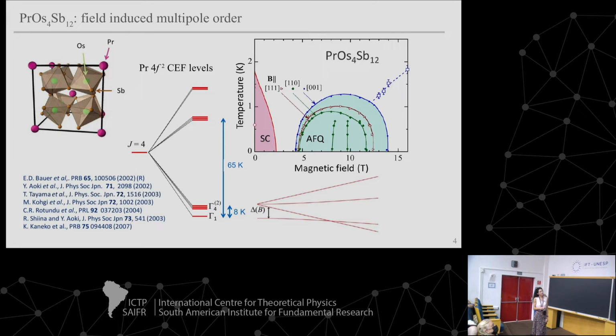When you put this in magnetic field, the magnetic field mixes, first of all, the gamma 1 and gamma 4 levels. And also the Zeeman splitting of the triplet causes a level crossing at this point. And this is what's allowing us to have the quadrupoles forming and ordering. So when you increase the field and these levels move closer together, you can't have a quadrupole and a singlet. You need a doublet for that. But in this region, you get a kind of quasi-doublet forming. And then you can form a quadrupole, and then the quadrupoles can order.